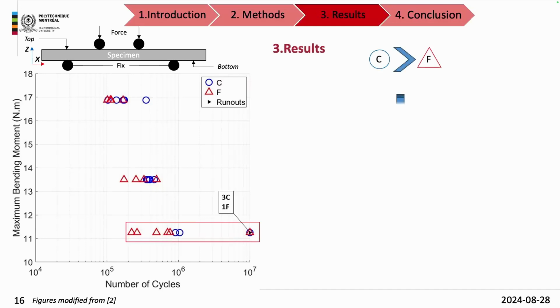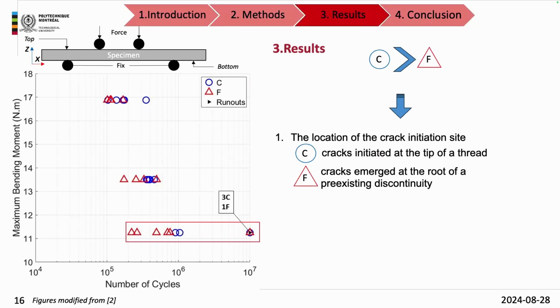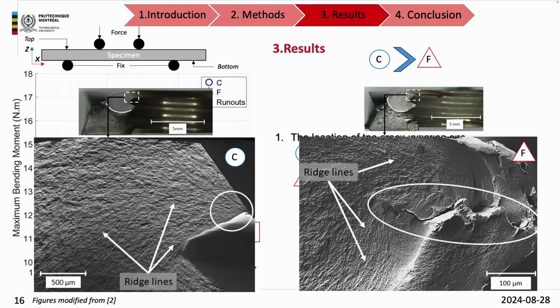Regarding the last loading level, we noted that the conventional specimen had a better fatigue life than the flow formed specimen. The main reason for that is, first, there is a difference between the crack initiation sites. When we look here at those images, we note that for the conventional specimen, crack always initiated from the tip of the threads, and on your left here, for the flow form specimen, there is a pre-existing crack, which is a discontinuity induced by the flow process, and more precisely, by the flow tapping process. And these discontinuities at a low loading level drastically reduce the fatigue life of the implant, since at a low loading level, we know that 80 to 90% of the fatigue life is to initiate a crack. So since we have a pre-existing crack, we reduced the fatigue life of this orthopedic implant.